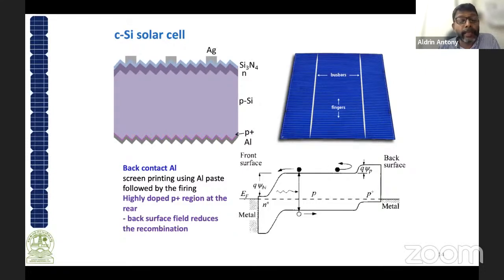And passivation means that if you are putting a material over the top, there will be a lot of dangling bonds on the silicon surface. That is the lone pair bonds of silicon, which will act as recombination centers. And these lone pair bonds can be passivated by putting this dielectric silicon nitride. And over that, we will have the contacts. And this is the structure of a normal crystalline silicon solar cell that you could see on rooftops or